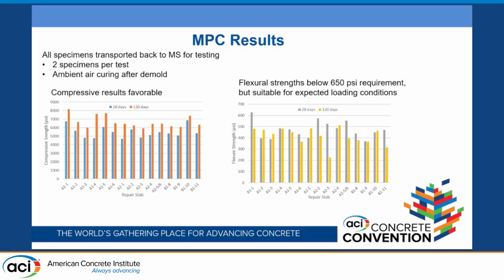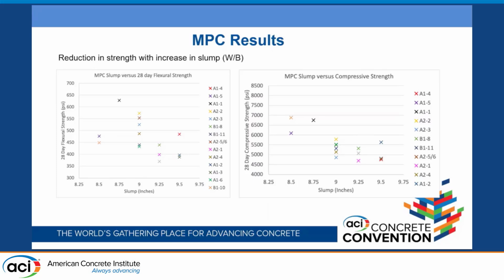So here's the MPC results. All specimens did get transported back from New Mexico to Mississippi for testing. Compressive results were favorable. We were generally above our 5,000 psi threshold. However, our flexural strengths were not as high as desired. We wanted 650. We ended up around 450 to 500. We did some quick calculations. The V-22 is one of the lighter aircraft, and so we figured that about 500 was tolerable.